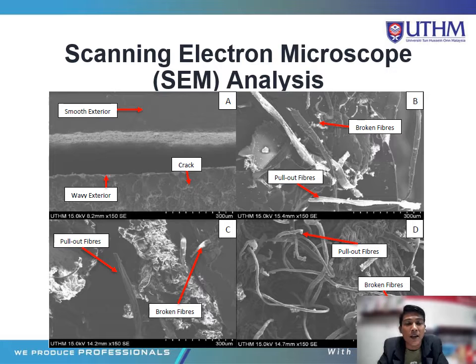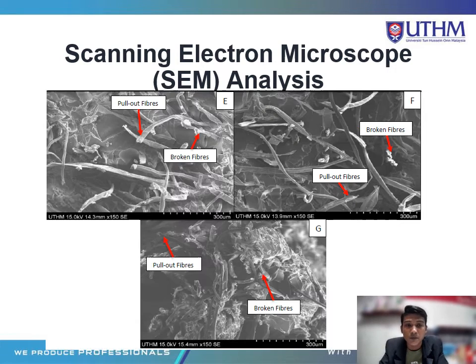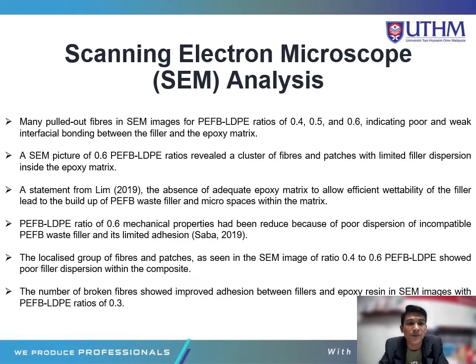This is my SEM analysis picture, which shows samples A, B, C, and D. On picture A, we can see the smooth exterior and also the cracked and wavy exterior. For picture B, we can see the broken fiber and pull-out fiber. Also the same with picture C, pull-out fiber and broken fiber can be seen, same as picture D. And for sample E, we can see the pull-out fiber and broken fiber clearly, and also for F and G.